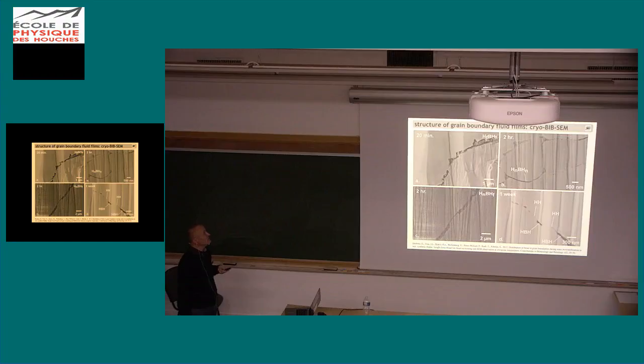Later, we got a new toy, which is the cryogenic ion beam electron microscope, and there we could freeze these grain boundaries with a fluid film and then polish them in cryogenic state with an ion beam. And these are actual images of these different fluid-filled grain boundaries made by Guillaume Dubois. He wrote a very nice paper about all the different kinds. And you can also see that in some positions these grain boundaries start to break up, which will come back later.